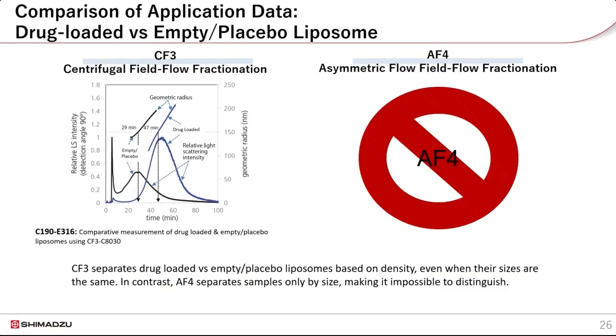One of the most common advantages of using CF3 over AF4 is the possibility to differentiate and separate drug-loaded and empty nanoparticles. As you can see in the results here on the left, the drug-loaded nanoparticles and placebo nanoparticles have the same size, but they can still be separated by the CF3 system based on their differing densities. The first peak is for the lighter but the same size of the empty liposomes, followed by a distinct separate peak for the drug-loaded and heavier liposomes. In contrast, AF4 is completely unable to achieve this kind of a separation.